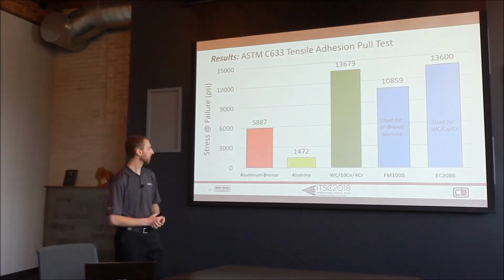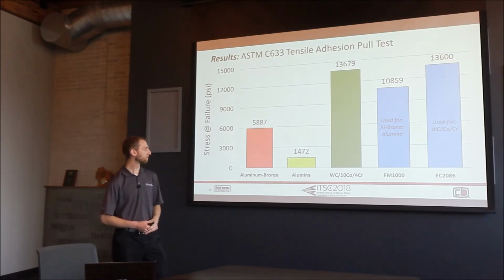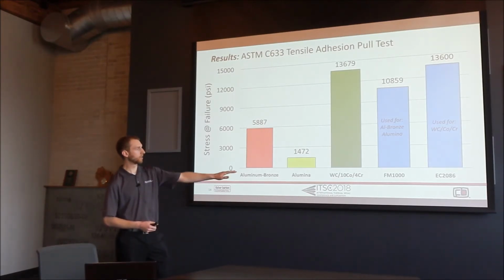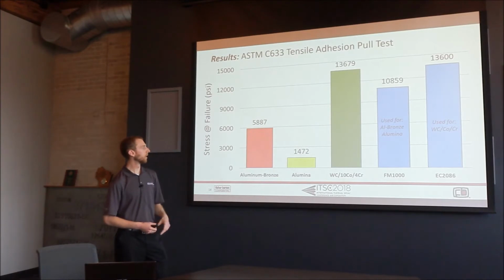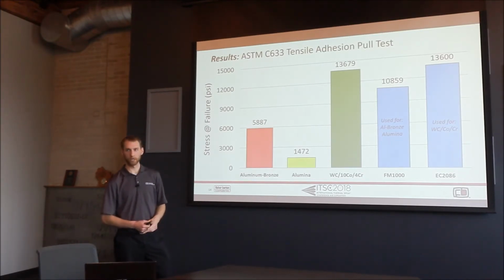Looking at the data here, aluminum bronze failed at about 6,000 psi, the fail point of the cohesiveness. Alumina was at about 1,500 psi. And then again, as we mentioned, WC/10Co/4Cr, in comparison to the 2 adhesives there in blue, the adhesive that was used, the 2086. In all 3 cases, the adhesion strength under tensile normal loading conditions was basically all due to the failure of the adhesive itself and not the bond strength.